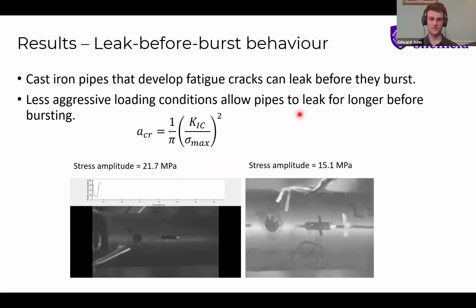And then finally, just the last aspect of this, expanding on this, comparing these two tests that we showed the videos for earlier, it's just highlighting again that when you reduce the stress amplitude by about a quarter, this test on the left leaked for about 10 cycles before bursting. The one on the right leaked for over 2,000 cycles, and we had to stop the test because of the amount of water we'd lost from the system. So reducing your loading basically allows these leaks to persist for much longer.